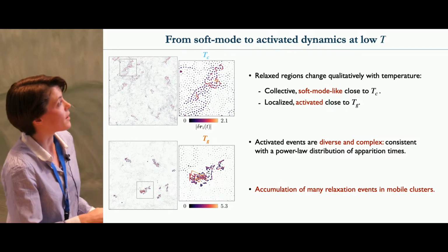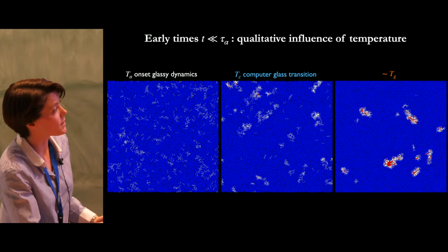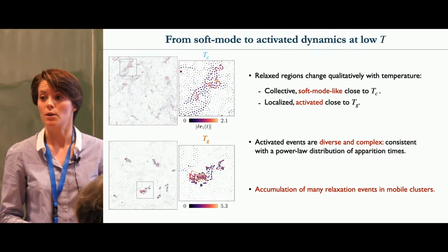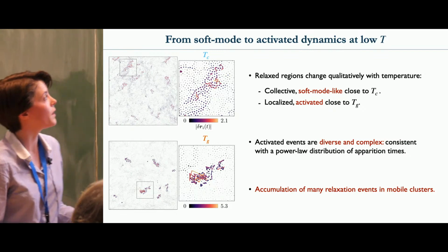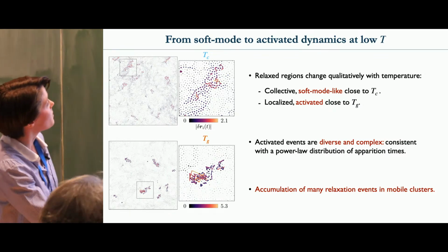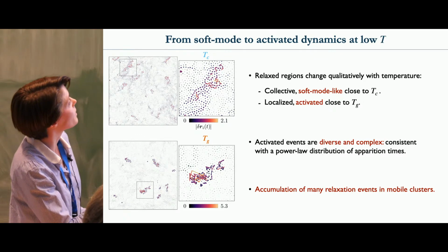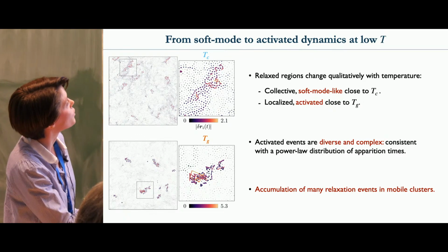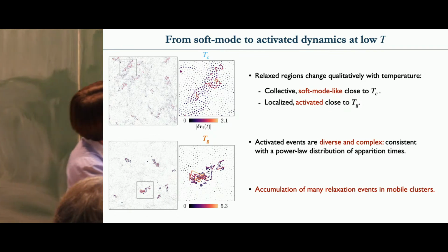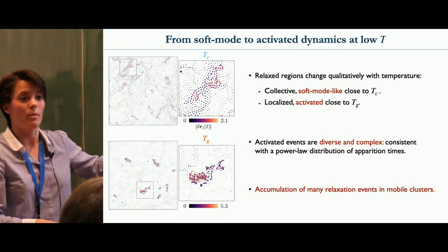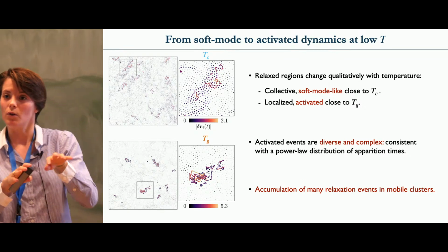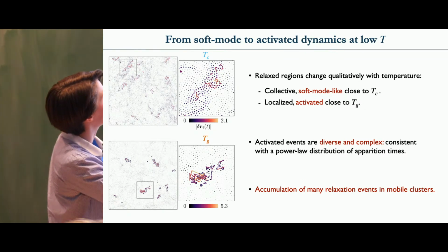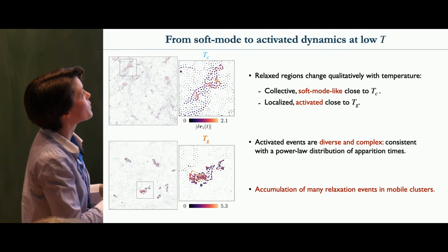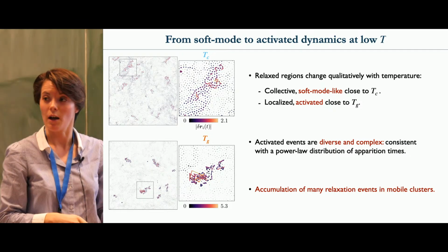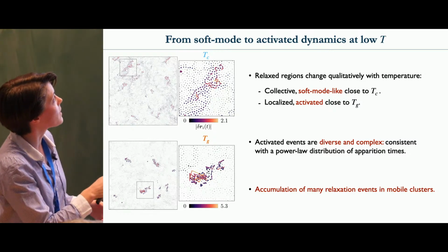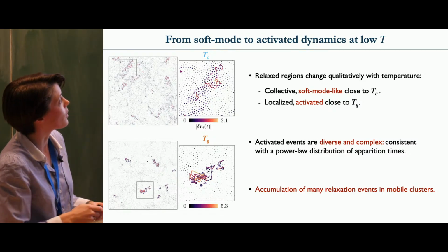For exactly these two snapshots, I'm showing the displacement fields of the particles so that you can have a better feeling of what's going on. Here at short times, I show the displacement field of the particles, and on the right, I'm showing this inset as a zoom. The particles appearing a bit in white, corresponding to just one or two neighbors lost, correspond to these very collective soft mode-like displacements that have been investigated a lot in the past. You see that the particles move collectively.